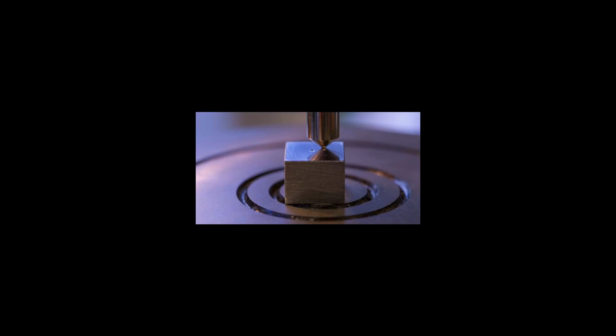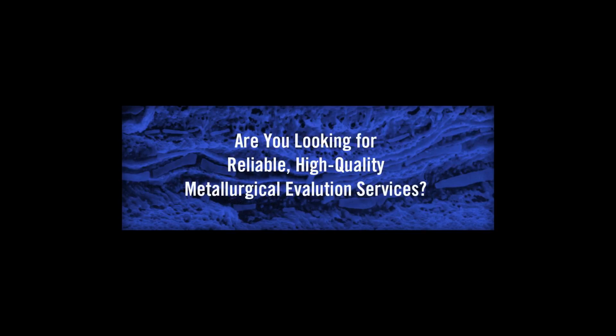X-ray fluorescence assay is not as accurate as fire assay, but dependent on the spectrometer used, can achieve results of within 1%. Fire assay, cupellation. The most elaborately accurate, but totally destructive, precious metal assay is fire assay. It may also be called by the critical cupellation step that separates precious metal from lead, if performed on bullion, high-purity precious metal alloy. To international standards, the method can be accurate on gold metal to 1 part in 10,000,